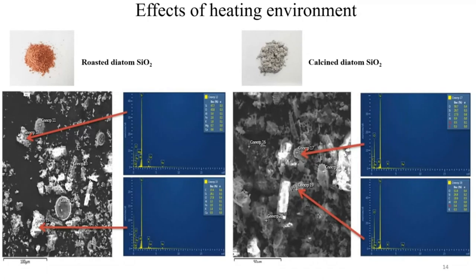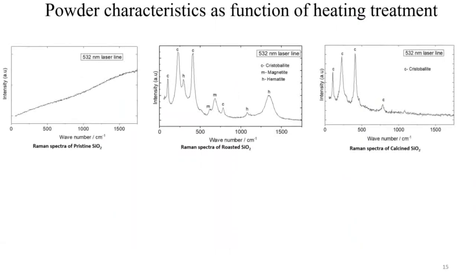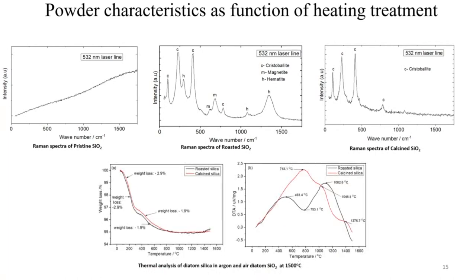And it was obvious that elements of iron, in elemental form or in an oxide form, played a role in the coloration effect here. Because in the case of the roasted diatom silica, the reddish color is quite typical for hematite, which is a type of iron oxide, which is not seen here in the calcined silica powder. Also, the powder characteristics as a function of heating. Again, Raman spectroscopy also confirmed the presence of phases such as cristobalite, hematite, and magnetite in the roasted silica powder, and the absence of such phases in the calcined silica powder.